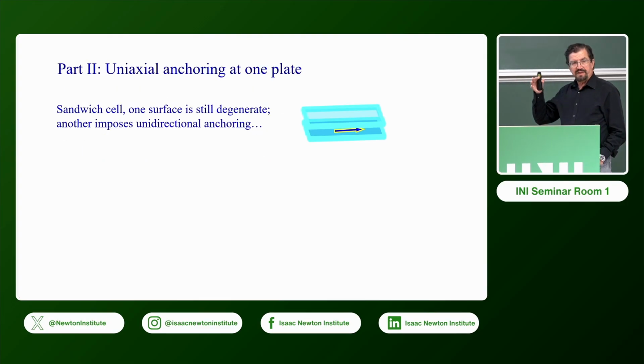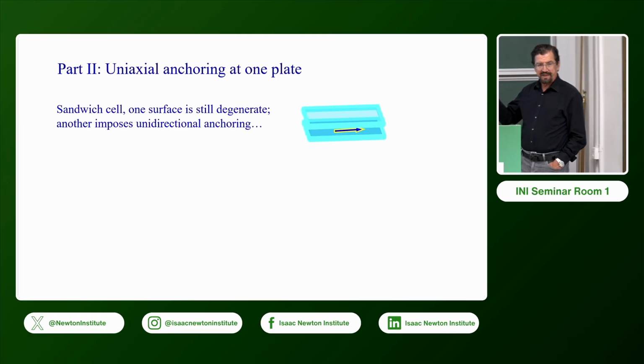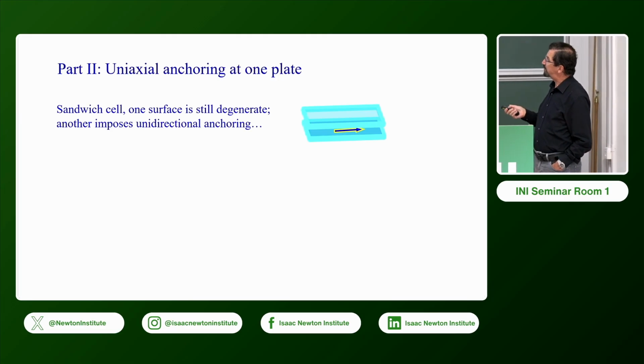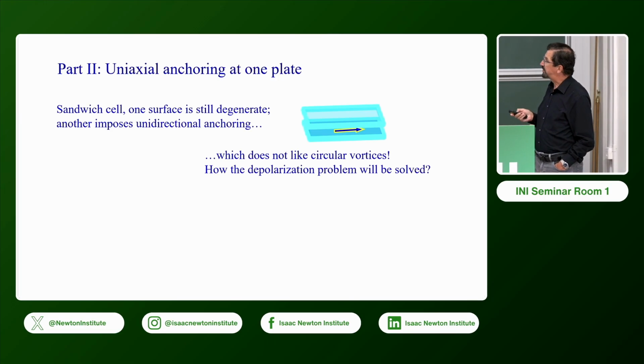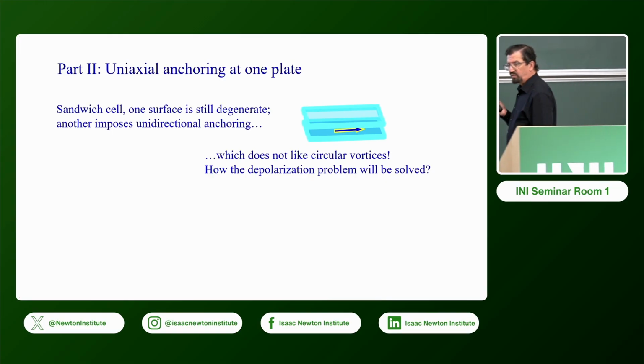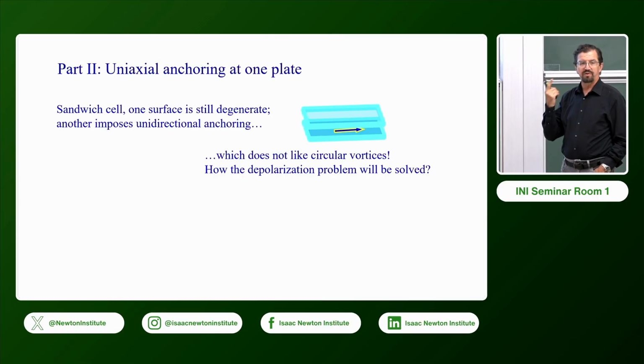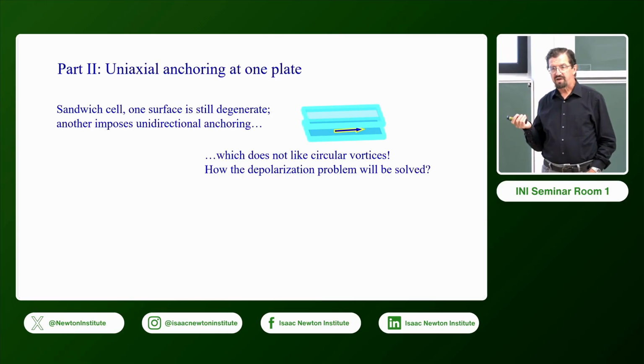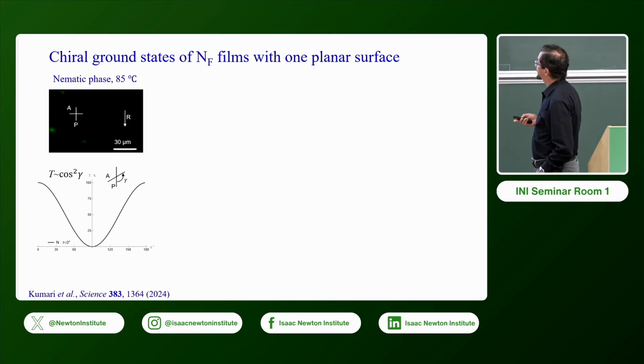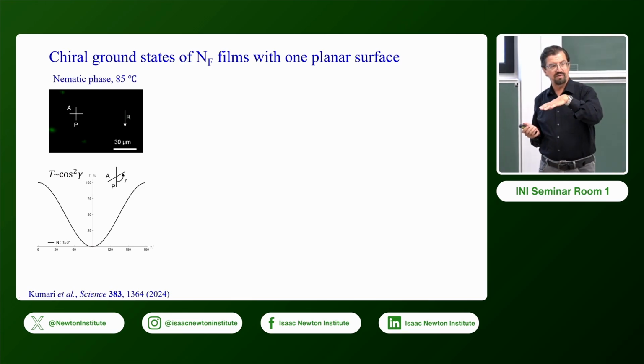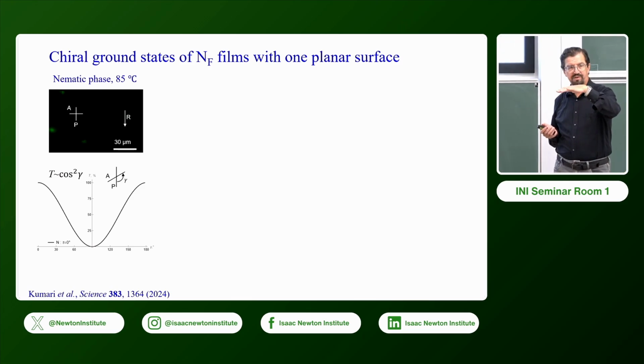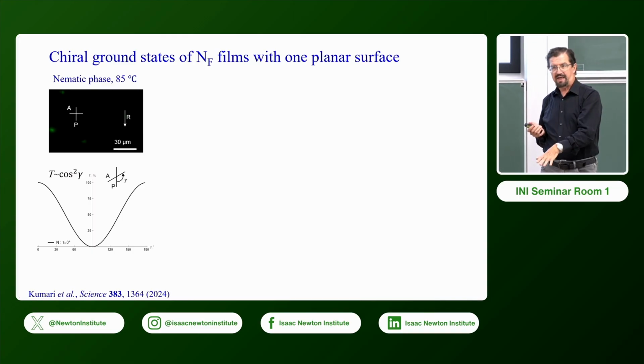So the next experiment is a little bit more complicated because one of the plates imposes unidirectional alignment. And of course, this unidirectional alignment would not like the circular domains. The question is how the texture would look. We can start with the material in which we have normal nematic, which is of quadrupolar symmetry, and polar nematic, which is the ferroelectric nematic at a lower temperature.